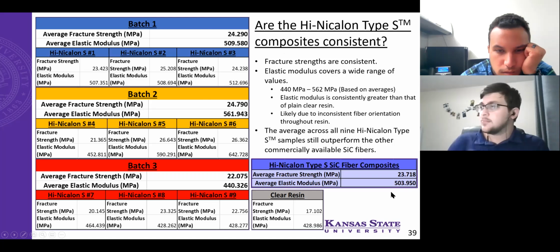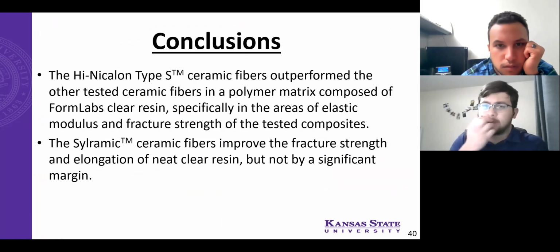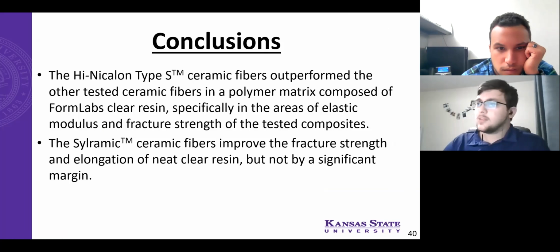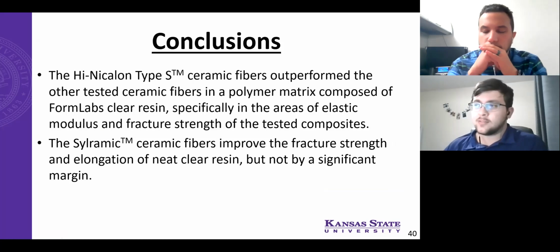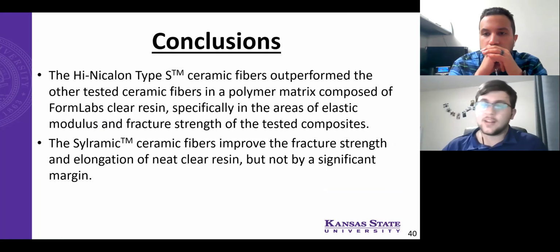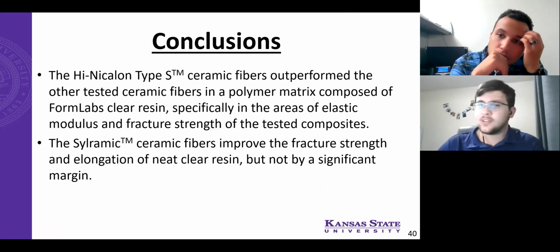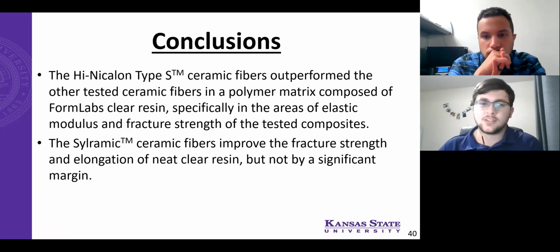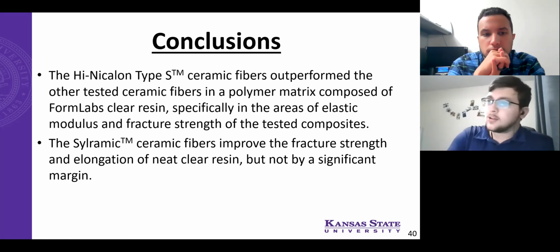And then conclusions from this data: the Hi-Nicalon Type S fibers seem to outperform the other tested fibers when looking at elastic modulus and fracture strength. And the ceramic fibers seem to improve the fracture strength and elongation of the neat clear resin, but not by a significant margin. And then the Sylramic fibers just seemed to underperform, and this could have been due to that pressing with the calipers that I mentioned. I see. Here are my references.